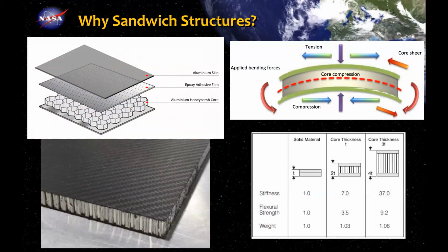So this bottom chart on the right shows you just a quick look at a solid material at a given density and a given stiffness. And you compare that to simply increasing to a core density, say about twice the thickness, you increase stiffness by 7 times, and by 3 times core thickness, 37 times. You can see the weight on the bottom goes from 1.0 to 1.03 to 1.06. So with about a 6% increase in mass, you can increase the bending or flexural stiffness by a factor of 37 times. This is the real reason why many of our composite structures win for space applications, especially when you consider buckling instability as a driving force when you launch. Next slide.